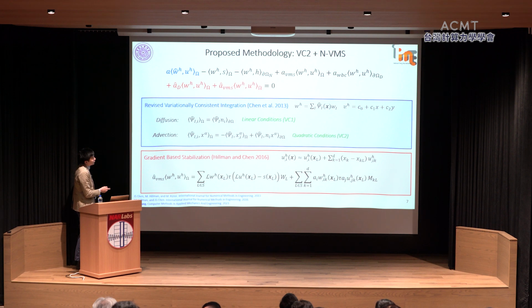So the idea here is I assume my trial function is a linear field, with a specific test function, and substitute into the weak form of the advection equation. For the diffusion part, if you check, you'll find out that the test function needs to satisfy the divergence theorem. That is actually called a linear constraint in the VC paper. But for the advection part, the tricky thing is you will find out that it actually requires the so-called quadratic condition in the VCI paper. So that means we need to impose an extended condition for the test function. The main point here is that even for linear approximation, you need a quadratic correction for the test function.